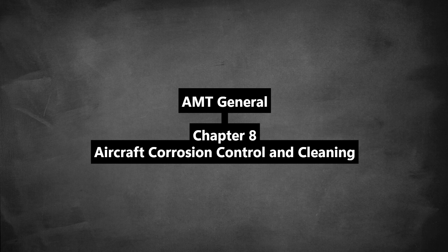Its corrosion products are typically white and quite voluminous. Early signs are etching, pitting, roughness. A thin, uniform oxide layer is okay, even protective. But attack accelerates with salts. Serious forms are penetrating pits, stress corrosion cracking, and intergranular corrosion, especially in improperly heat-treated alloys.